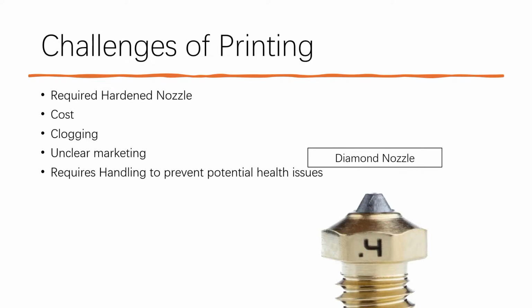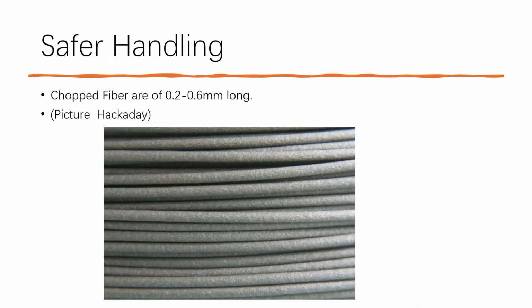Okay, and now the challenge of printing carbon fiber filaments is that you need a harder nozzle, because the carbon fibers are pretty stiff. You will grind out your non-hardened nozzles. There are problems with clogging, and also the cost of carbon fiber is higher than regular filaments. Now, some other problems with printing carbon fiber filaments: there's a lot of unclear marketing. Many of them don't tell you what type of carbon fiber is in there. They don't tell you how to handle it properly. Also the percentage in there. So this is actually a pretty big problem in our industry. And also there are some handling considerations when you're working with this kind of material.